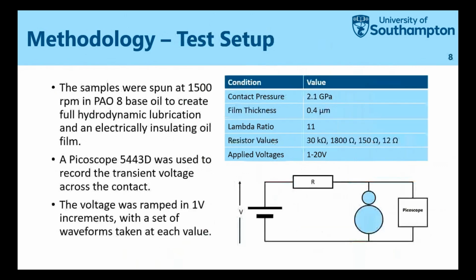For the two tests I'm about to present results for, I ran a sample pair in, and once that happened, we applied voltages between 1 and 20 volts, with different resistor values swapped in and out, to generate discharges across, in this case, a fully lubricated contact with a very high lambda ratio.